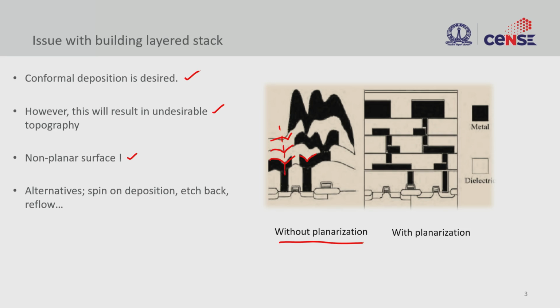If that is the case, your layers are not going to be of equal thickness. For instance, this black region is a metal region, but the metal thickness here and the metal thickness here are going to be different. And you see a section here that could result in failure, because the resistance in this particular contact is going to be very high, and you could have serious failures here. Ideally, what we want is this sort of flat geometries. You want everything to be flat to start with.